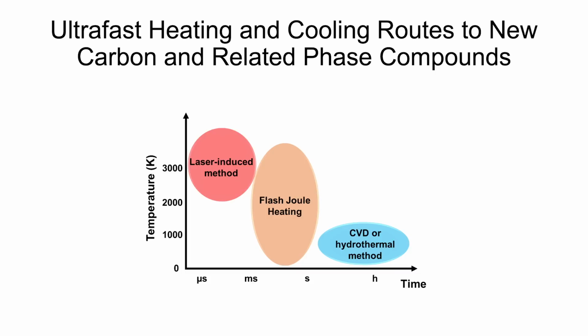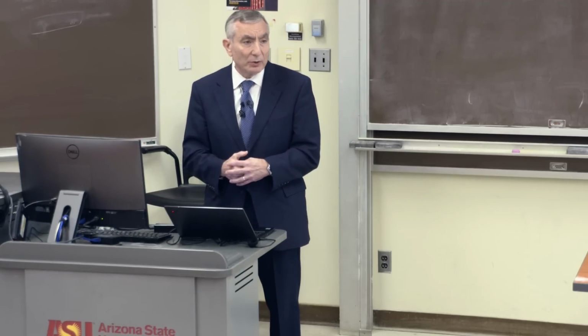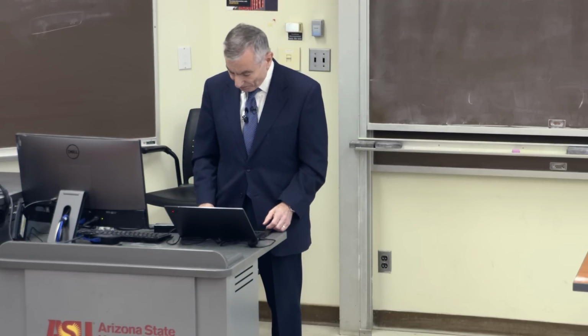So flash joule heating is usually done in milliseconds to seconds, so it's very fast, and you can hit an entire temperature range. You can easily be up over 3000 Kelvin. So you can heat very quickly, and it cools very quickly. And because you're heating and cooling very quickly, you can trap things in high entropy states, if you like, and make new materials that way, and we'll discuss that today.